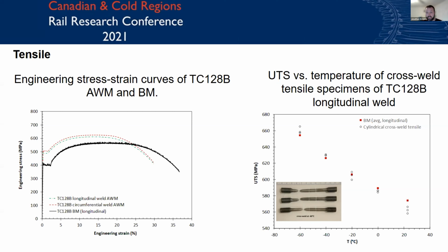What we like to see is the samples failing in the base metal rather than the weld, which is exactly what we saw in these samples. We also see the weld metal follows the same trend as the base metal, which is a reduction in tensile strength as the temperature increases. And even over this relatively small temperature range, there is quite a significant change in the strength of the material with temperature.